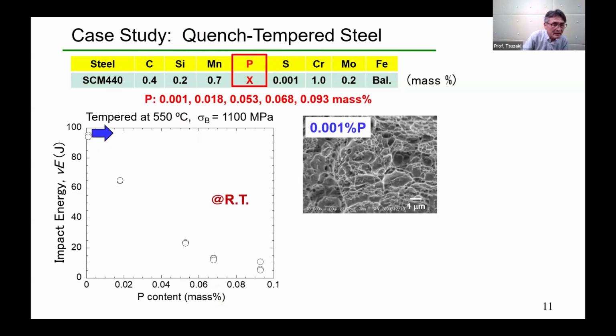The impact energy at room temperature shows more than 90 joules when the P content is 0.001%. And the fracture surface shows dimple fracture. And impact energy decreases markedly with increasing P content like this.